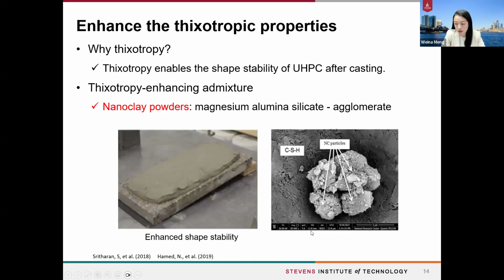So for the second problem, related to the slope casting, the effective method is to enhance the thixotropic properties of UHPC, because the thixotropy can enhance the shape stability of the UHPC after casting. As you can see, with high thixotropy, the UHPC can stay on the sloped panels, which can help us to minimize the formwork and other construction-related costs.